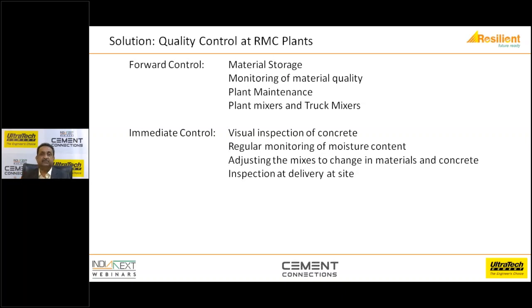There is a practice where for dust suppression, water is sprayed on the fine aggregates. It's fine, but it also means that if you don't remix the sand properly, you might get a higher moisture content of 10% in one part of your sand bin, and the other part of your sand may be relatively dry with 2 or 3%. So this can play havoc in your slump and in your workability.